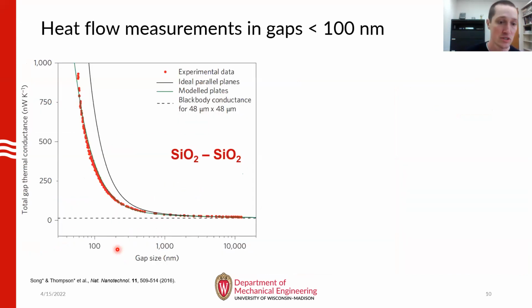So here you can see the central results of this experiment, where we plot the radiative thermal conductance between the pads as a function of the gap size. And in this experiment, both pads were comprised of silicon dioxide. So as you can see, we're able to sweep the gap from over 10 microns all the way down to around 55 nanometers before contact was established. And at the smallest gap size, we observed over 100-fold enhancement in the conductance compared to the estimated black body conductance, which is captured by the horizontal dashed line down here.